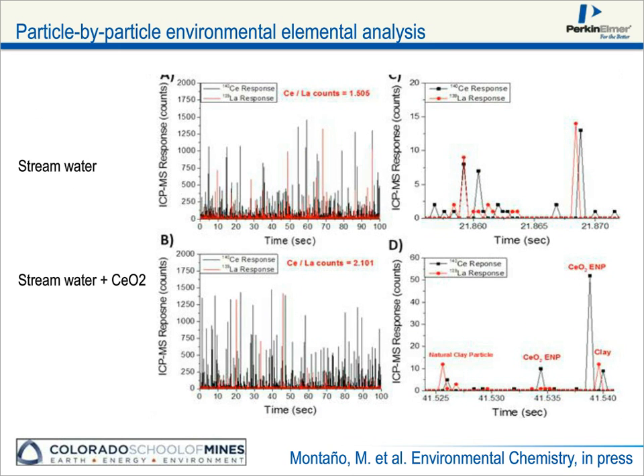On the upper right, you can see for the most part, and this is a work in progress, we see cerium and lanthanum occurring together. And as we introduce cerium oxide into the system, we start to see more and more cerium-only pulses. Again, this is a work in progress, and further work needs to be done to look for what levels of cerium are really required for us to statistically be able to count cerium-only particles from those containing both elements.